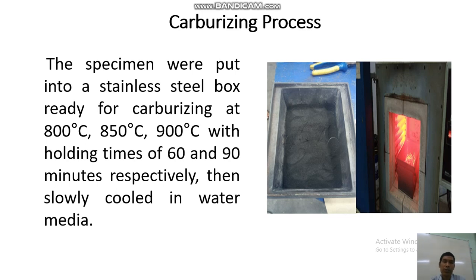Carburizing process. The specimens were put into a stainless steel box ready for carburizing at 800 Celsius degrees, 850 Celsius degrees, and 900 Celsius degrees with holding times of 60 and 90 minutes respectively, then slowly cooled in water media.